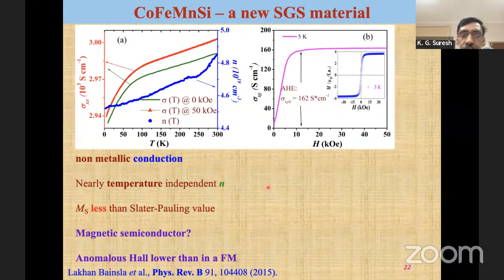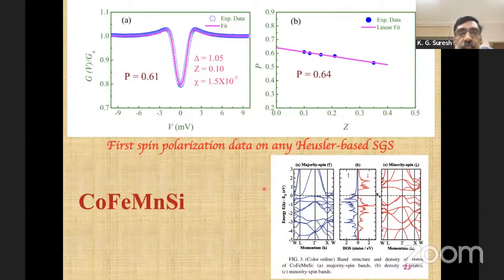Then if you have theoretical support, you can actually find out the band structure, and that is what is done in this particular case. You can see that here, the band structure is exactly what I showed you. There is almost a zero gap for the spin up channel, and the semiconducting properties are seen, and the spin polarization also comes because it's essentially a spin polarized material with a gap of zero energy. Therefore, you expect a decent spin polarization. You can see something like 61% spin polarization as measured by the PCAR data.